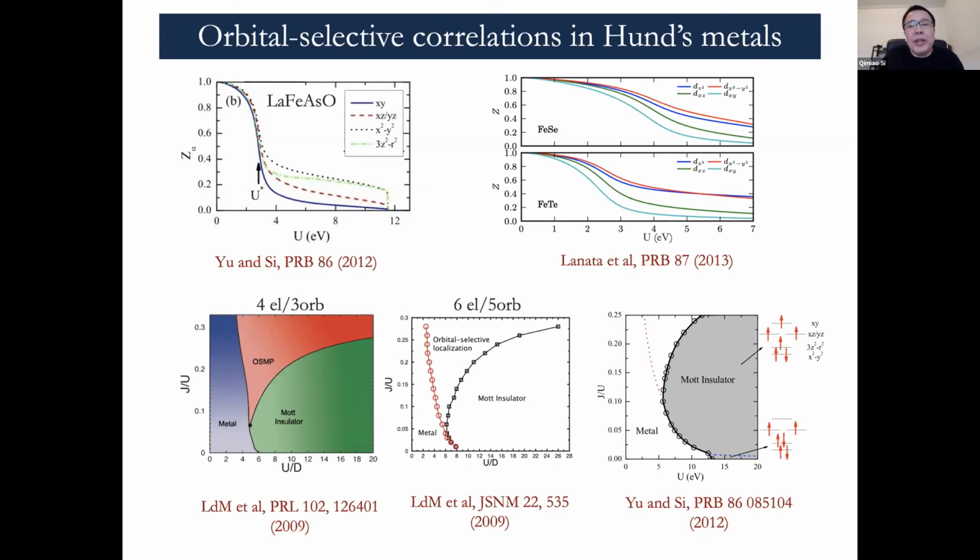terms of enforcing whether the XY orbital is close to half filling, closer to half filling to be strongly correlated. Because if you want to get a mass enhancement, you have to move the entire filling closer to half filling. And the lower Hubbard band is a very important feature for counting the filling. So I guess that's sort of an overall comment. I don't know whether you agree or disagree, but the question to you, well, is...